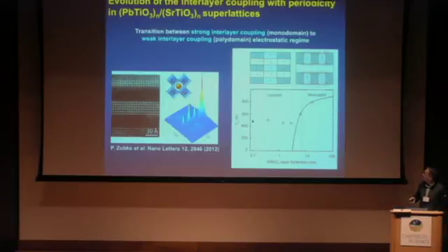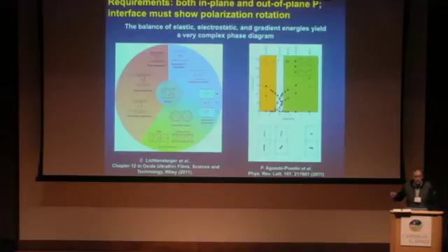But these electrostatic degrees of freedom are not the only thing that is important in this system, because they are also prone to have a polarization rotation imposed by the in-plane lattice constant of the substrate. In particular, a compressive strain favors a 001 polarization, the so-called C phase, while a tensile strain favors a 110 polarization, the so-called AA phase. And in the middle, and very interestingly, in regions very close to the lattice constant of strontium titanate, there is a continuous phase transition, a continuous rotation between the C phase and the AA phase. So there is some tendency for the polarization to rotate.